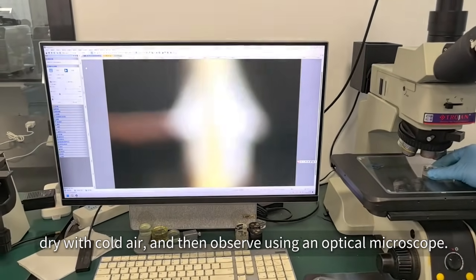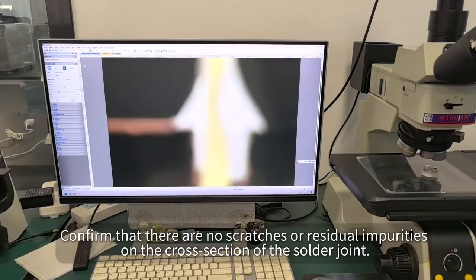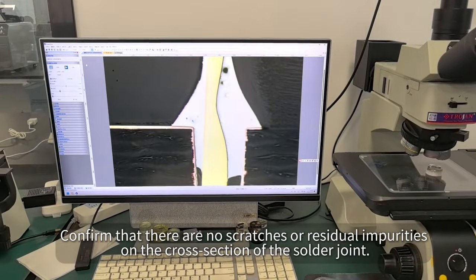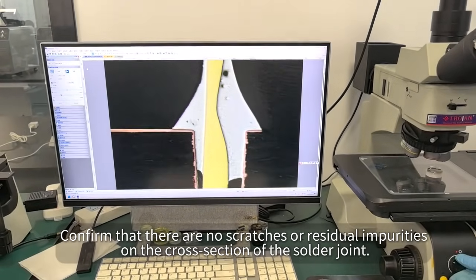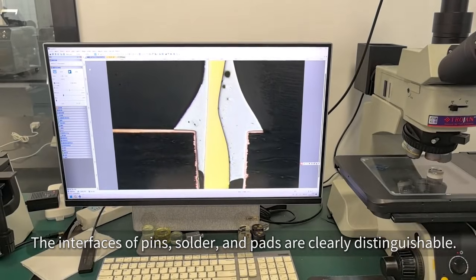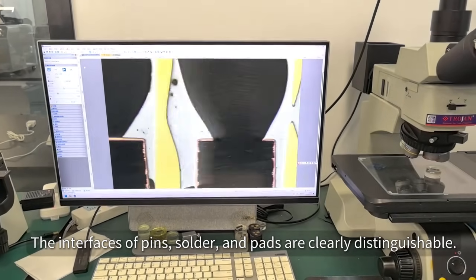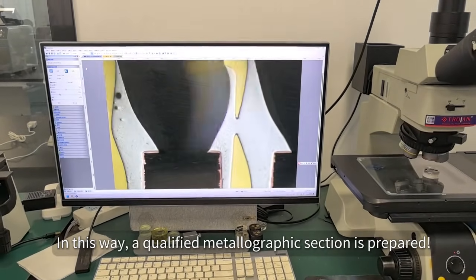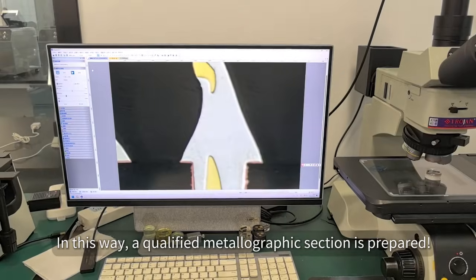Dry with cold air, and then observe using an optical microscope. Confirm that there are no scratches or residual impurities on the cross-section of the solder joint. The interfaces of pins, solder, and pads are clearly distinguishable. In this way, a qualified metallographic section is prepared.